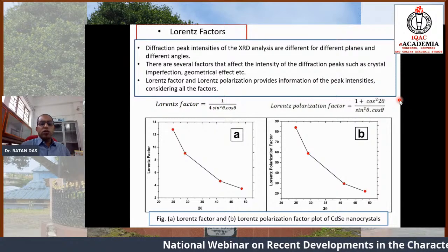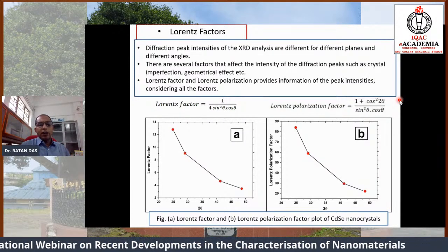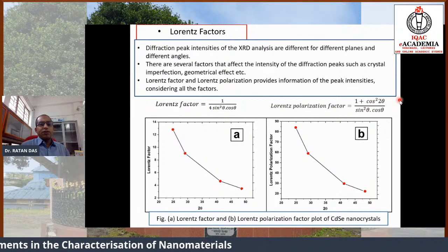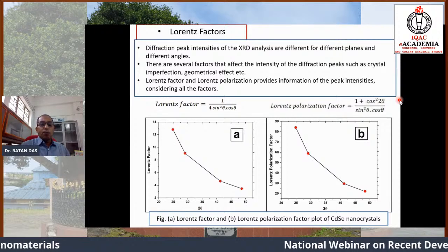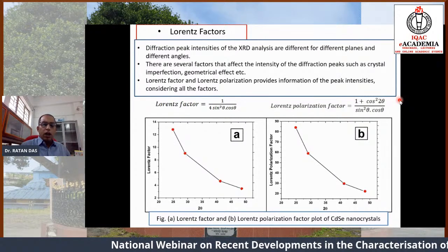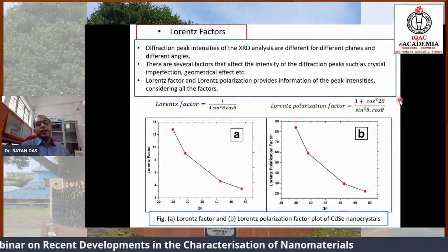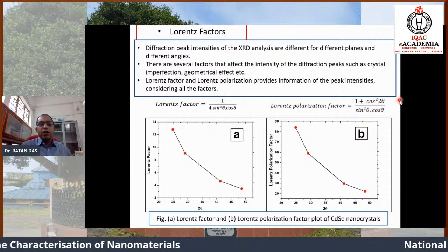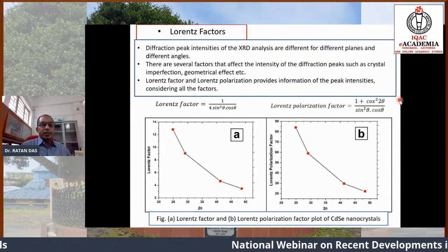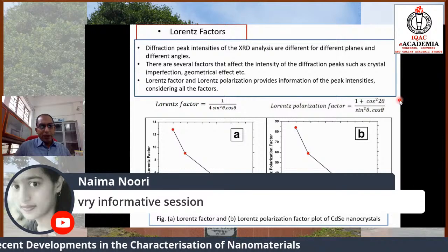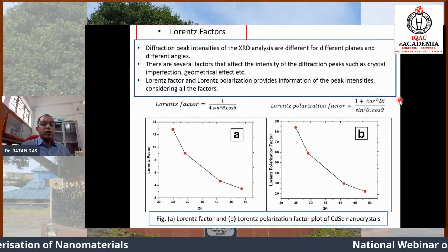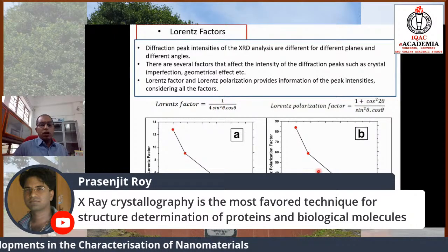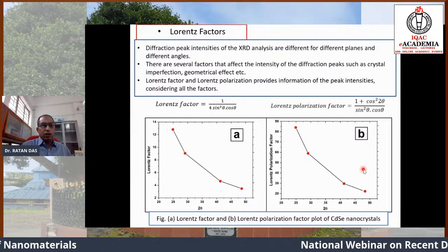There are also the Lorentz factor and the Lorentz polarization factor. These factors also play a major role in the X-ray diffraction peak intensities. If you take the X-ray diffraction pattern of your bulk sample, and then the pattern of your nanoparticle sample of the same material, there may be a vast change in peak intensities. Or if we have a sample and take the pattern after doping, there may be a change in the peak intensities. The Lorentz factor and Lorentz polarization factor play the role in the peak intensities, and those factors can be obtained easily if anyone goes through the literature. That's not the issue.